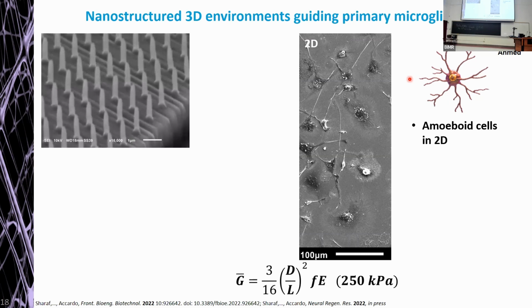That's the trick. The effective shear modulus, which is represented by this formula over here, is the shear modulus sensed by a cell when it is crawling over a carpet of compliant nanostructures. So when these nanostructures move, even if the material itself, which in this case was IP-Dip, the 1.8 gigapascal material of the first example that I showed you, the cells actually feel it much softer because it's not bulk. That is why it's called effective shear modulus. And that depends, of course, on the coverage of the nanopillars and on their aspect ratio.